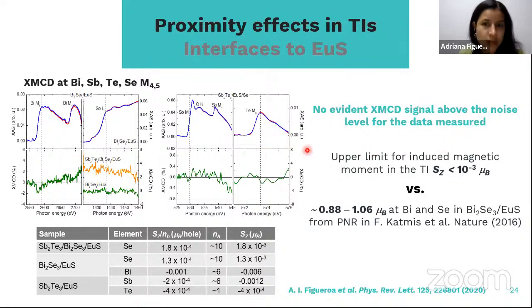But by application of the sum rules here, we are able to establish what would be the upper limit for the induced moment in these signals that we measure. We see that the spin moment that we would see would be below 10⁻³ Bohr magneton. And this is in stark contrast to what has been reported, for example, by other studies in polarized neutron reflectivity measurements for these kinds of systems of TIs with europium sulfide, where they report magnetic moments up to 1 Bohr magneton that we do not see. And then what we demonstrate is that indeed we don't have proximity effects. We don't have induced moments on the TIs.